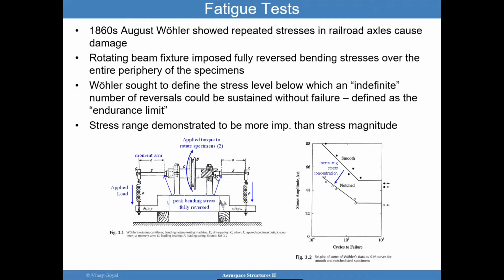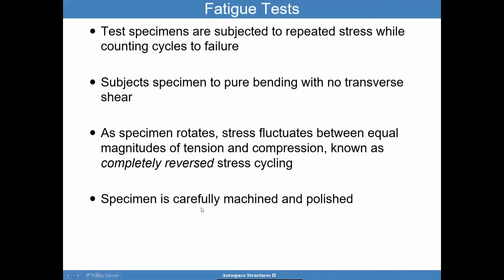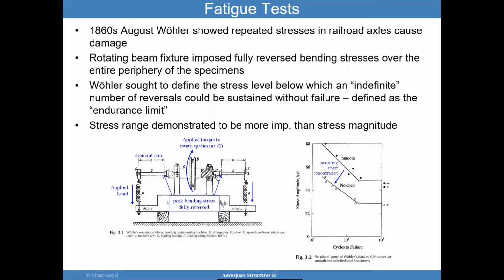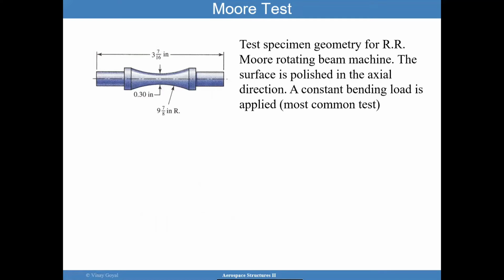And so if you have a notched sample, it will decrease the strength, the fatigue curve. So this is stress amplitude versus cycles to failure. And then if it's smooth, then he got this data. Now notice that there's scatter in this data. That's one of the things we're going to see, that even though your specimens are carefully machined and polished, it can still give you scatter in the data.